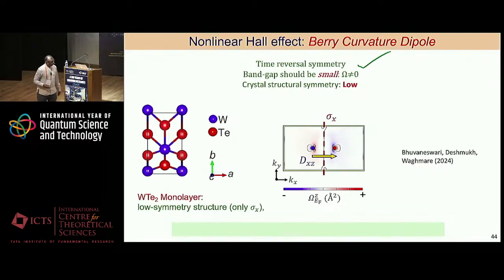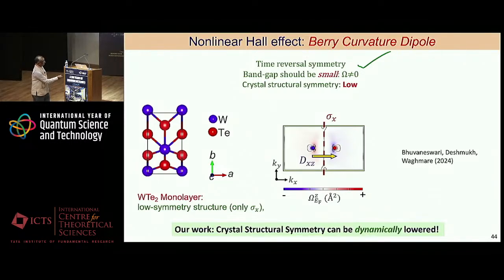So Bhuvaneshwari, which Mandar also referred to in his talk, we calculated the Berry curvature dipole of the non-centrosymmetric tungsten telluride and find that this is the Berry curvature distribution in the Brillouin zone, and it has a dipole moment because there's only one mirror reflection symmetry in the lattice. And basically, this is to get started. You need to have low symmetry to have a non-zero Berry curvature dipole.